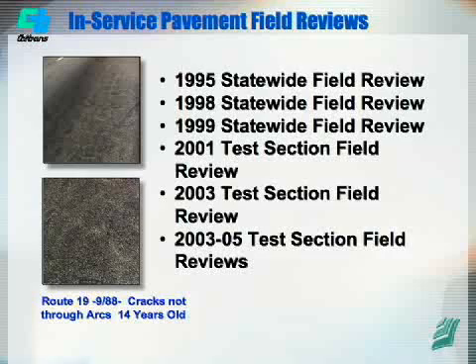And one of the benefits of the reflective cracking benefits of asphalt rubber is amazing. Even when the cracks show up, they don't open up the way the cracks open up with conventional asphalt concrete. They always stay tight, and that's the nice thing. So you get a smooth pavement that continues to be smooth even when you have cracks.